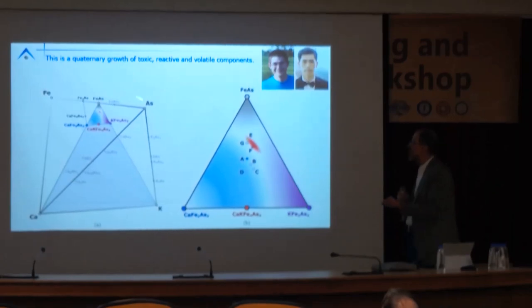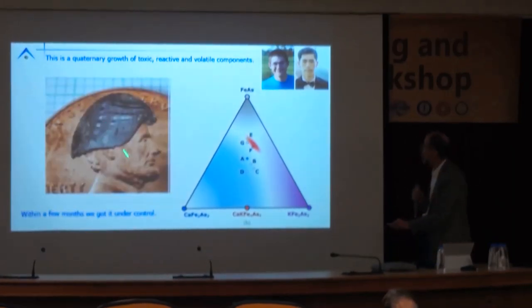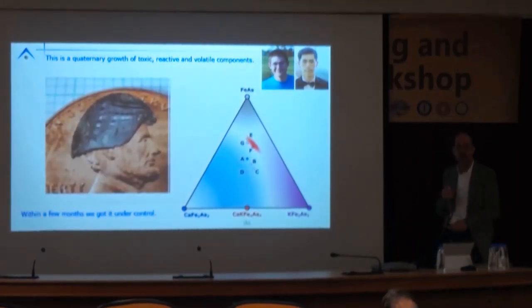The compositional phase space is a tetrahedral volume. Okay? We can actually take a pseudo-ternary cut shown here, and they dropped down a number of growths, and we figured out if you took a pseudo-binary cut between iron arsenic and the 1144, we had a very narrow access to a primary solidification. But with that determined, we could grow beautiful single crystals of these materials.